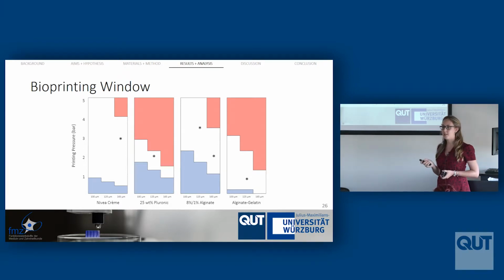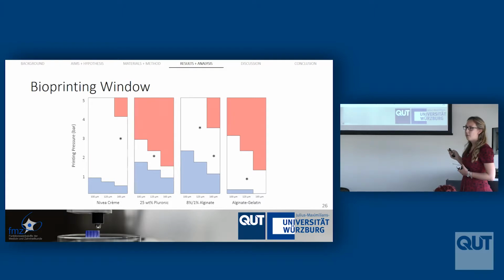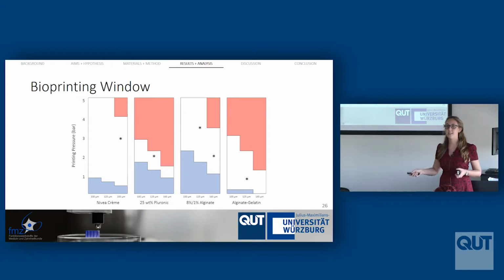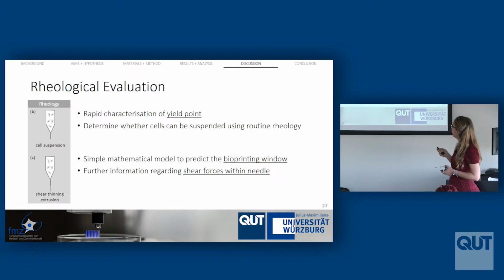So we can now use this mathematical model, which is very simple. It's actually just an Excel spreadsheet, to be able to tell us automatically for any material whether there is a window within what our printers are capable of with different needle radiuses and also printing pressures to be able to tell if that material is printable. And so these tests take half an hour with the rheometer, and this mathematical model will tell us whether we can suspend the cells during printing, but also tell us about the shear forces within the needle and whether the materials fit within this bioprinting window.